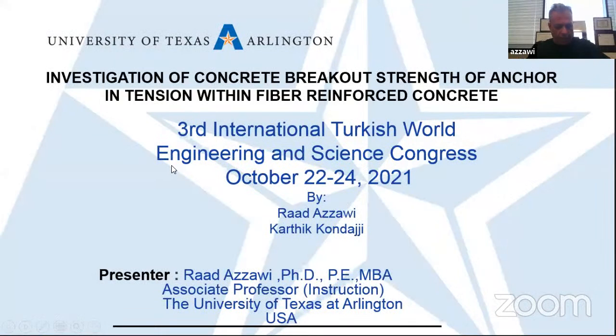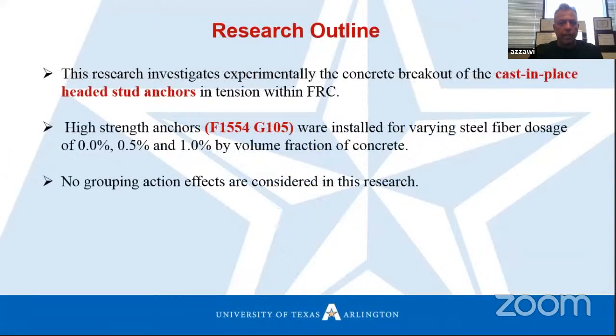Yes, Dr. Rajab. So this research is going to investigate the concrete breakout strength of anchor in tension within fiber reinforced concrete. I did this research with my colleague Karthik here at the UTA, and this research investigates experimentally the concrete breakout of cast in place headed stud anchors in tension within fiber reinforced concrete. We use high strength anchors F1554 grade 105 and installed for varying steel fiber dosage for different mixed designs, 0%, 0.5 and 1%.